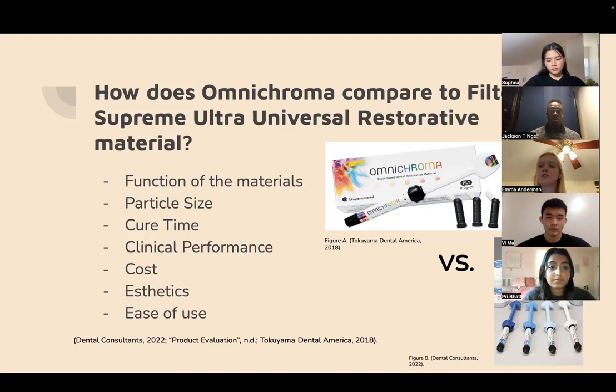In clinical evaluations, Filtek ranked slightly better for compressive and flexural strength, both still reporting above average. Omnichroma ranked better for a balance between the volume loss of the composite resin and the wear of the tooth, as well as overall aesthetics. They were the same for their ability to resist stains.